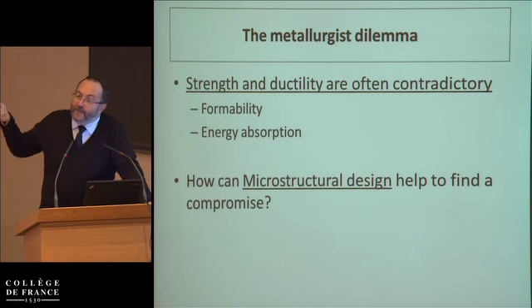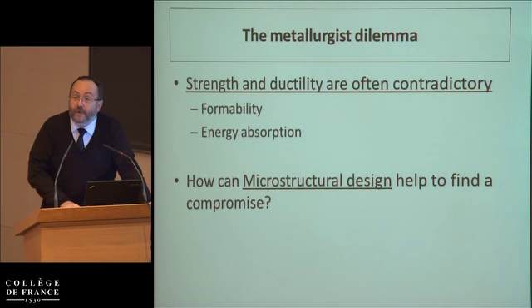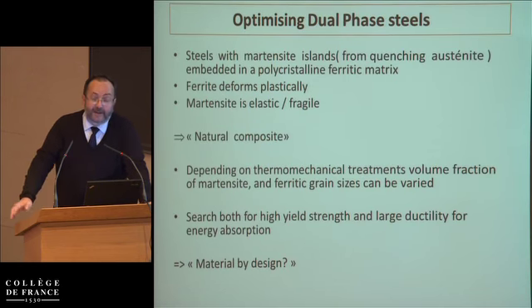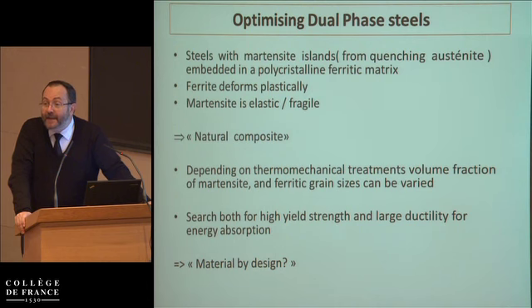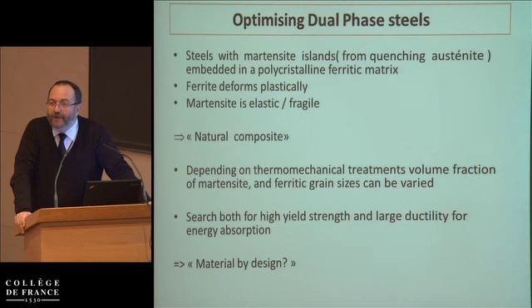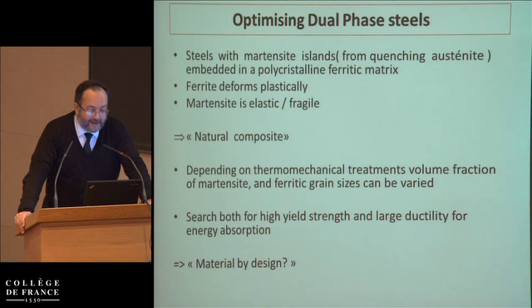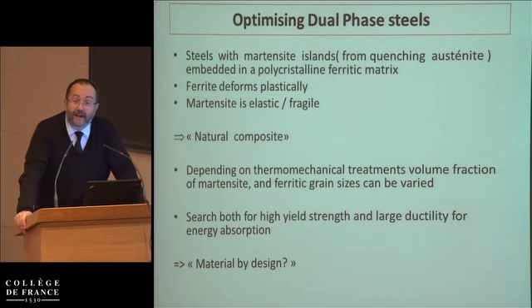Now, that's something which came from the composite material, but which is reused in classical material, which are called the dual phase steels. So the dual phase steels is basically a natural version of the composite material. Natural meaning that you don't mix the inclusion inside the matrix. So there are steels with martensite islands, which are coming from quenched austenite. They are embedded into a polycrystalline ferritic matrix. The matrix deforms plastically. The martensite is elastic and fragile, and that's a natural composite.